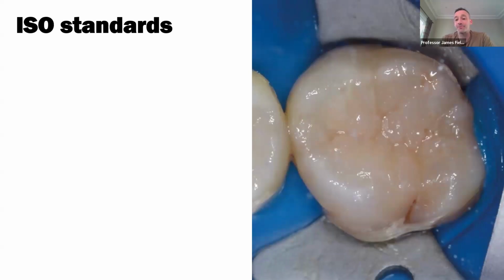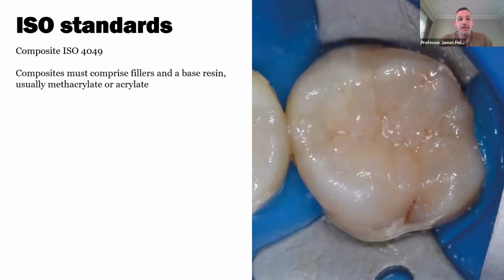So let's move away from that anyway, because we're not using amalgam anymore. Let's turn our attention to composite, and this is bound by the ISO standard 4049. And I think it's really useful to go through some of these characteristics because, again, we often forget what we're using and the kind of the material that we are using and the choices available to us. But composites have to, according to the standard, comprise a base resin, which is usually methacrylate or acrylate based. And then it has to comprise fillers, which go into that base resin. And mixed together, it makes this kind of paste of varying viscosities, which we can use to apply into cavities or to shape into different shapes before curing.